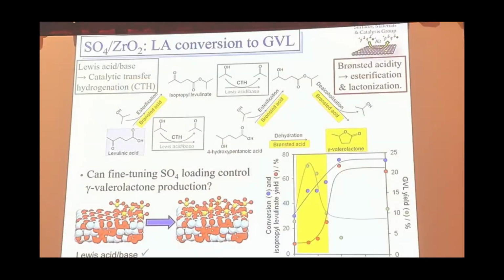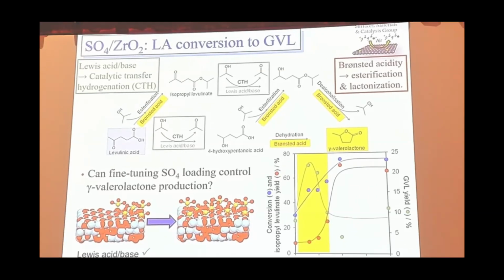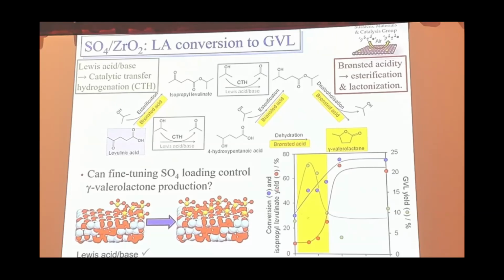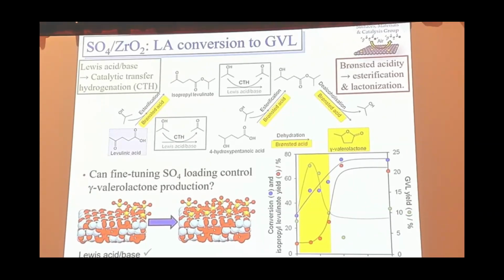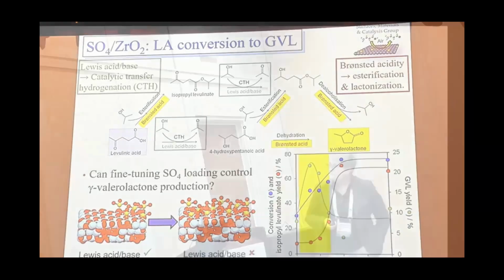So down here in this partial coverage regime, you're able to have an acid site to do the initial esterification, but still enough Lewis acid and Lewis base sites to do the catalytic transfer hydrogenation. So when you go to very high coverages, you eliminate all of your Lewis acid-base sites, and all your catalyst can do is esterification. So this system, although it works, is quite limited because out here you can see the conversions are relatively low. So we thought, is there anything we can do to try and improve on this?